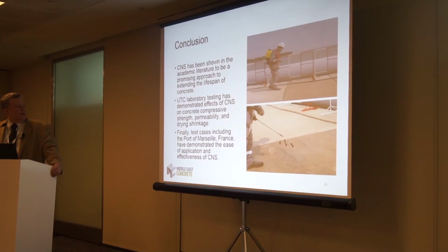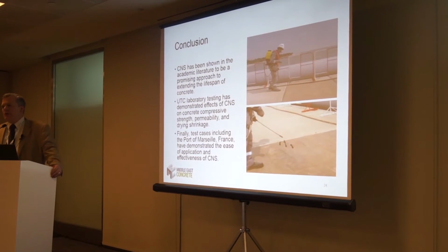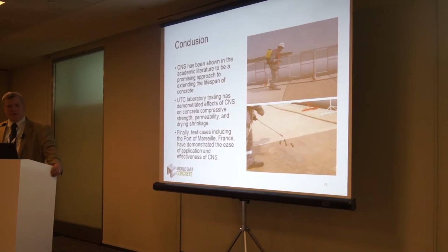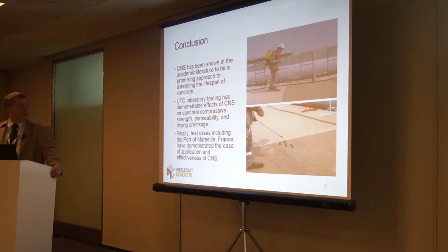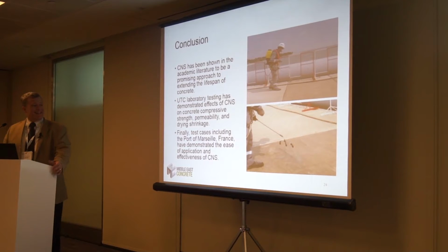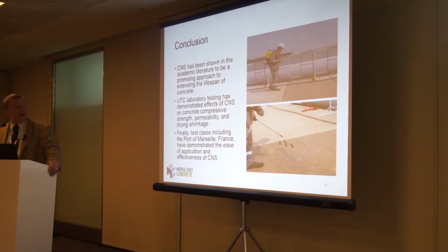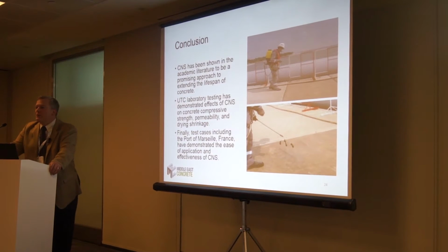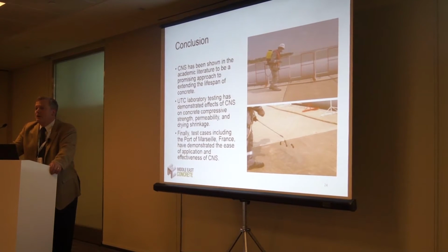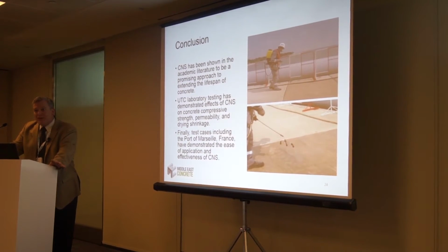But finally, the test cases, which include the Port of Marseille, as well as others now that have been done, have demonstrated that it's an easy product to apply, and that it's effective. When we saw 0 cracks on the Port of Marseille boat dock, we got lucky, but at the same time, if it hadn't been there, I'm confident there would have been some random cracking occurring. So that wraps up the presentation.